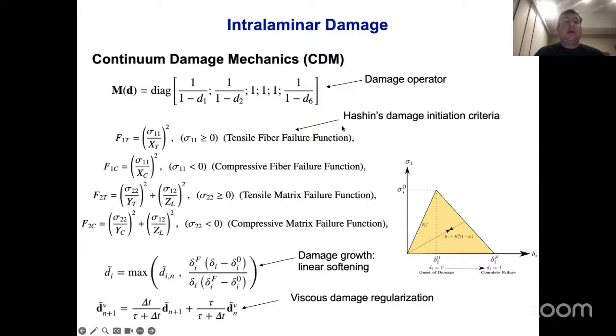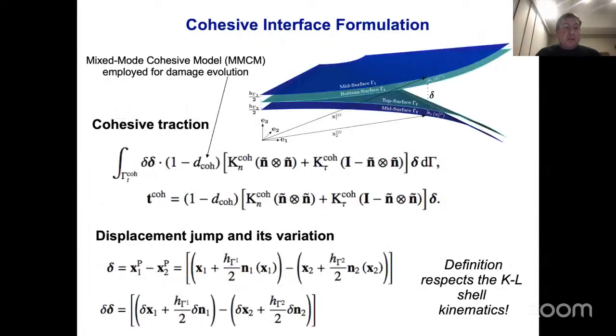This is the damage operator. We use, as I mentioned, Hashin's criteria for damage initiation. We have 4 modes: compressive and tensile fiber failure function, and tensile and compressive matrix failure function. We track the modes individually using a bilinear law, linear softening here. Then we convert the damage indices into the damage variables associated with fiber, matrix, and shear. And we use a little bit of viscous regularization to improve the overall performance of the nonlinear convergence of these procedures. To simulate delamination, what we do is we add a term like this to our overall formulation connecting all the plies. Delta here is a displacement jump, or what's known as a separation, between the different plies. That defines a traction-separation relationship that takes in the separation.